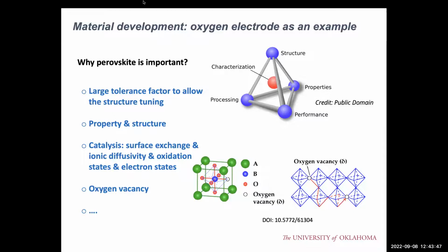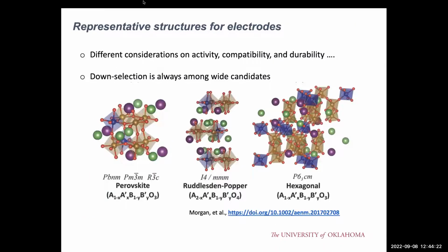And because of this kind of doping, you can tune your properties like the electrical, the mechanical, and the catalytic activities. So you can tune these properties by changing the composition. And the perovskite can tolerate this kind of structural change. And also because of this tuning, we can easily change the properties on the surface and also the bulk to accommodate this application. This slide shows some typically used structures, like the perovskite and the Ruddlesden-Popper structure. We typically call it the RP structure. And among these different material candidates, as I mentioned, the perovskite is the main material system I have studied before.